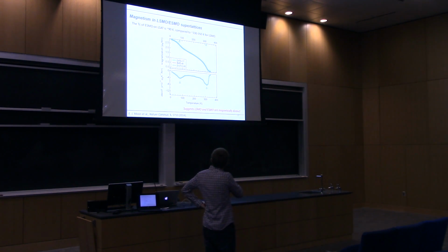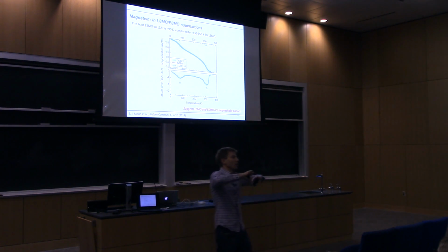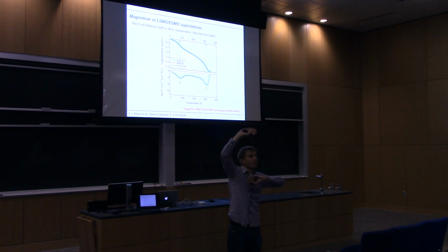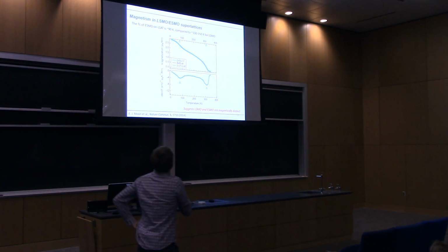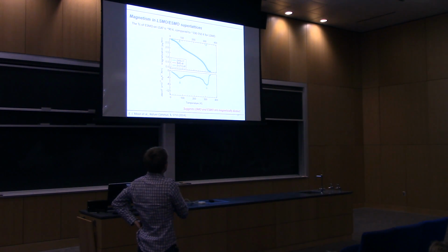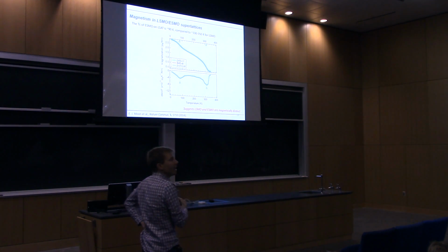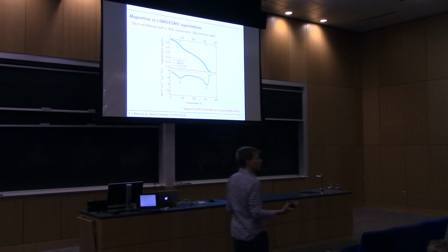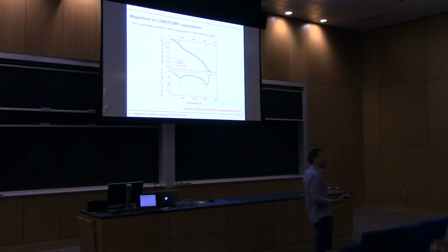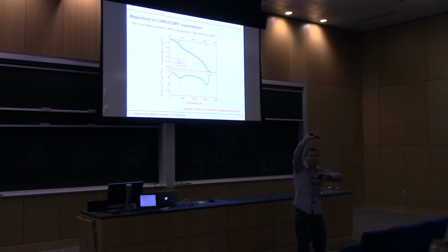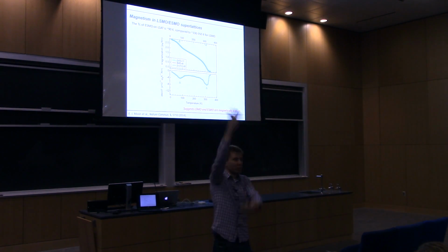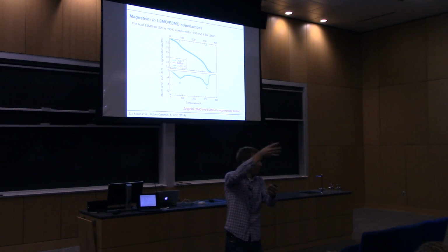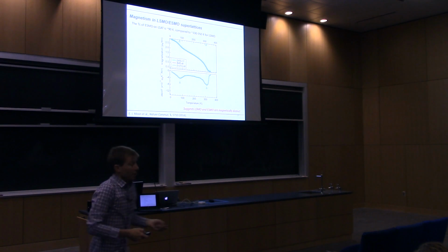One occurring, and again, this is the 11-11 superlattice. So we're starting with the interfaces as far away from each other, so we would expect the most modulated structure. All right, and so here we see a Curie temperature around 320 Kelvin and one around 80 Kelvin. These match up very well with the bulk lanthanum strontium manganite and europium strontium manganite. So this suggests that the LSMO layers are acting like LSMO, the ESMO layers are acting like ESMO. Right? We push them far enough apart that whatever this interfacial perturbation is, it's not dominating the physics. Okay, that's what it looks like.